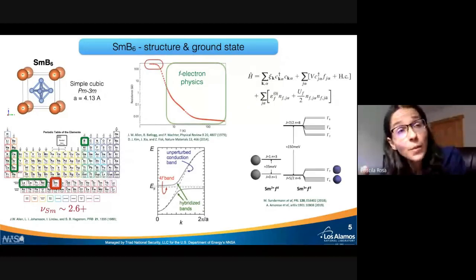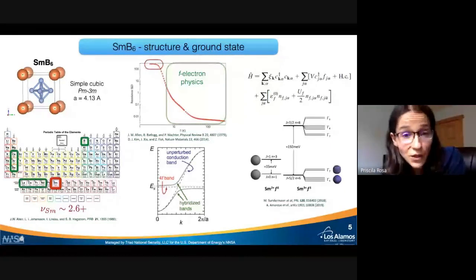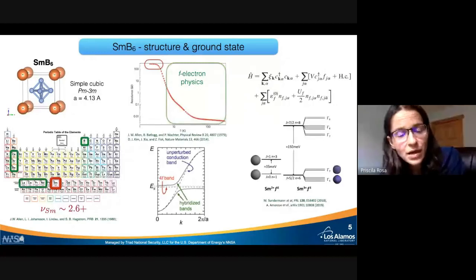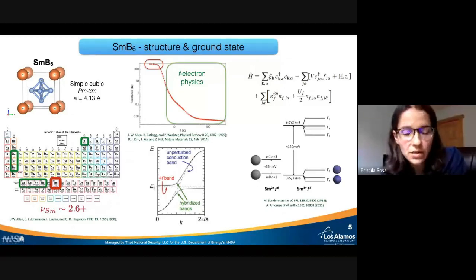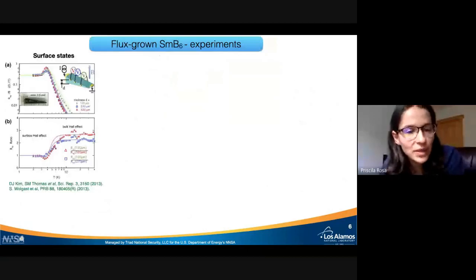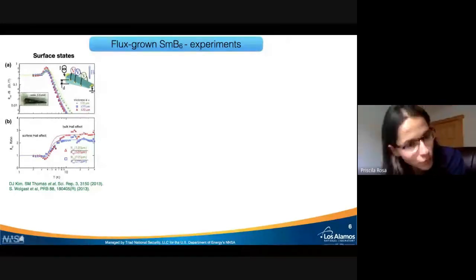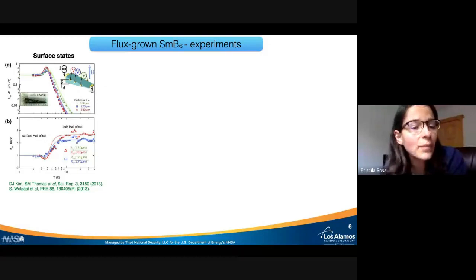And if the topological insulating state is correct and exists, then there should be surface states in this material. So a lot of investigation has been done in this material at low temperatures to see whether this is actually a surface state. So let me show you some examples. This is a very clever measurement here of Hall versus temperature. And by measuring the Hall effect at various thicknesses, this group showed for the first time, actually there were two groups that showed with different techniques pretty much the same thing, that below, let's say 4 Kelvin, the conduction is dominated by the surface state.